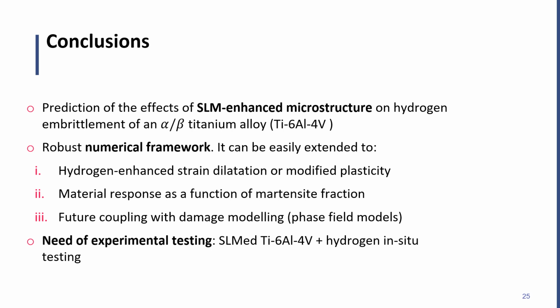To sum up, we recall that the objective of this work is to predict how selective laser melting is expected to modify microstructure, especially the martensite fraction, and this will affect the response to a hydrogen environment. This modeling framework is complex, especially for an alpha-beta titanium alloy, but here we have demonstrated that hydrogen accumulation and hydride formation can be implemented. For time reasons, we did not discuss strain dilatation or modified plasticity, but we have already implemented these phenomena in Abaqus subroutines. The following step is to predict crack propagation using the coupling of our framework with phase field models. And of course, we are also starting with experimental testing on titanium-64 produced by selective laser melting to verify our model predictions.